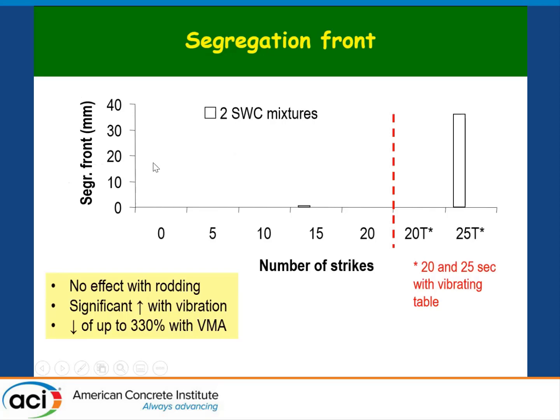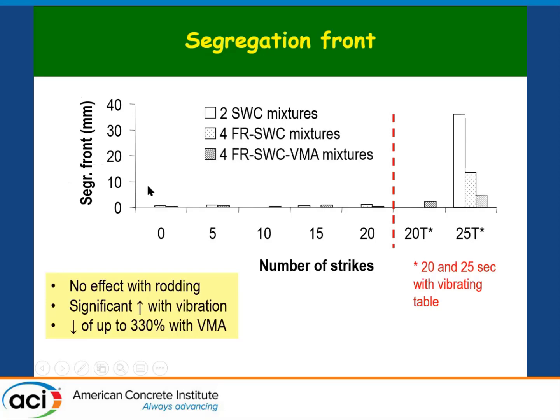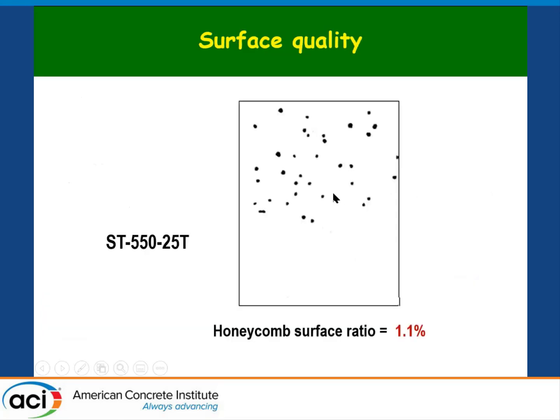And the segregation front, which is another index of evaluating segregation. Again, we see over here that the striking did not really influence the segregation. 20 seconds was fine, but if you go 25 seconds, a lot of vibration energy, unless your mixture is very stable, you're going to have issues with segregation.